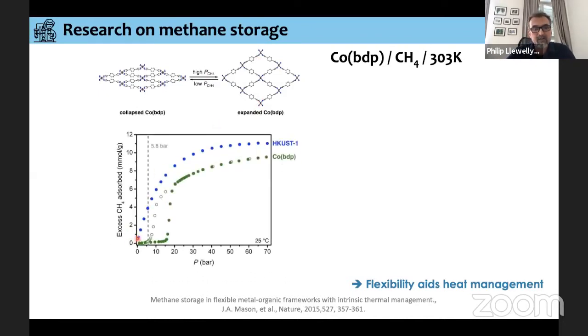Just as a comparison, these blue dots here are for a rigid or fairly rigid structure known as copper BTC, HKUST-1. And this is in green, the isotherm they obtained with this material. So initially, no adsorption of methane in the material until about 15 bar. And then this pore opening, going from here to here, into the open pore structure. And on desorption, they see a hysteresis.